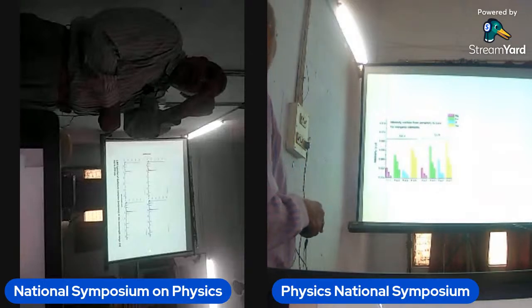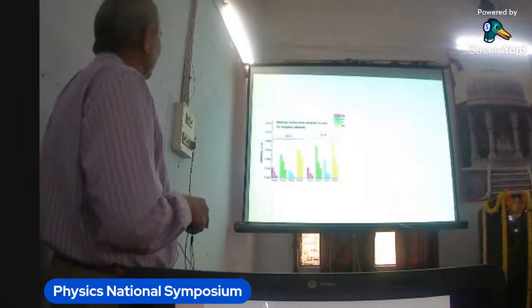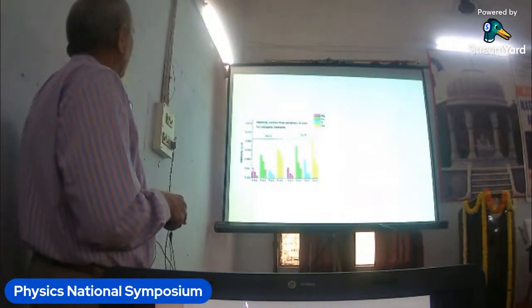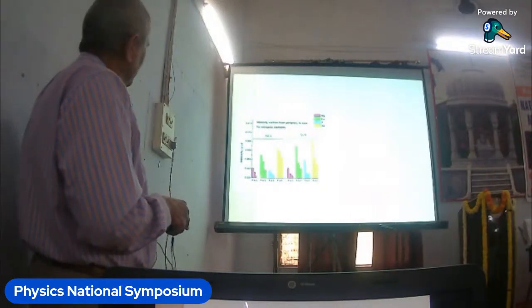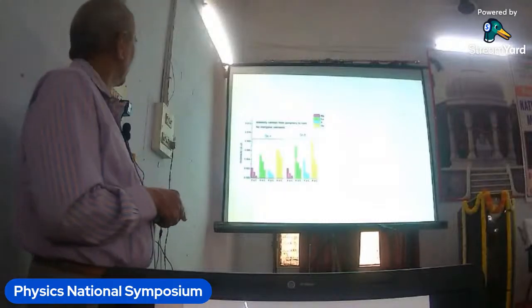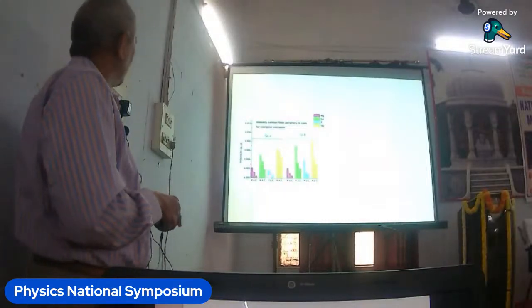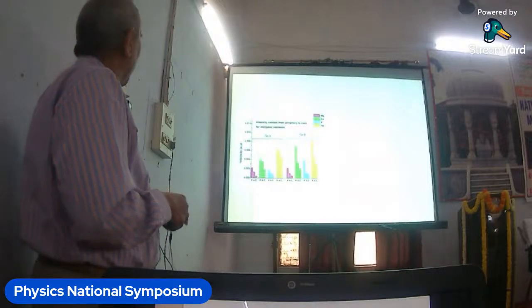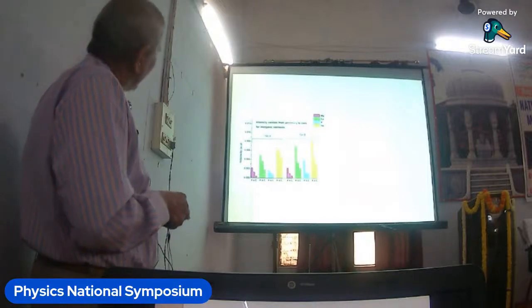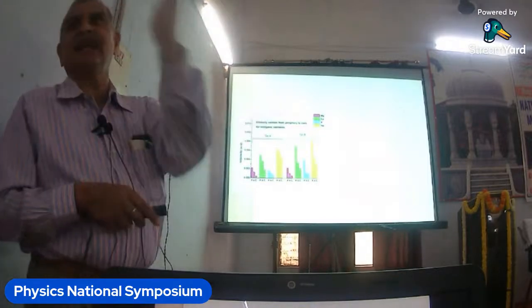So we have measured the intensity of the spectral line of different elements, for example, magnesium, calcium, potassium, and sodium. And here you see that if you go from periphery to center, the intensity of the magnesium line decreases and becomes minimum at the center. It is similar in the case of calcium, and similar for potassium as well as for sodium. And this result is also the same if you analyze another gallstone.